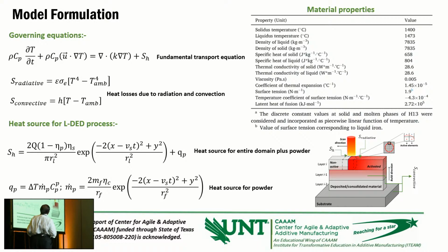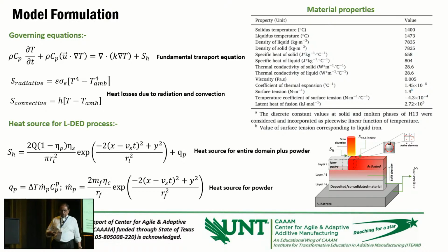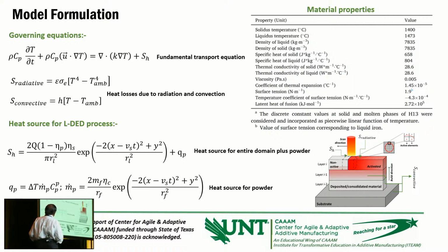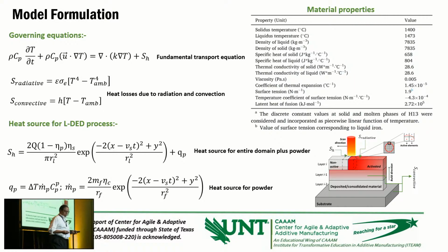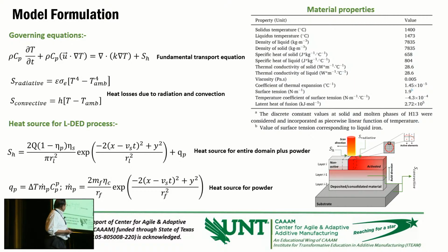Basically, this is a very standard fundamental transport equation. Then you have heat losses due to radiation and convection when the laser beam interacts with the material and starts melting and solidifying the material. The heat of the interaction is lost by radiation and convection, which are predicted by these equations. And now the heat source for laser direct deposition, a powder injection process which we are using, has a different equation compared to the steady state powder bed process. So you have to formulate the equation accordingly. One thing you have to keep in mind, in this process we have used the Gaussian beam distribution. The energy distribution of the laser beam is in Gaussian form, so that equation is incorporated here.